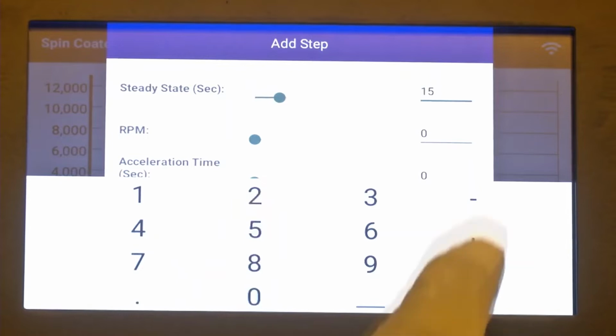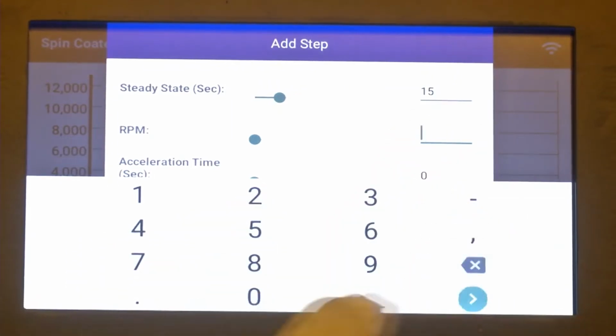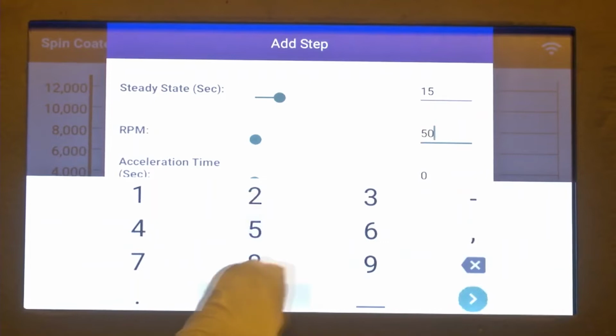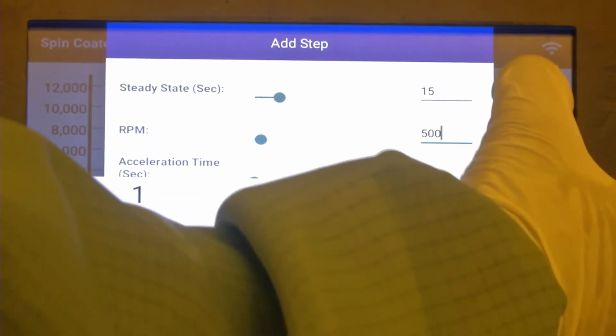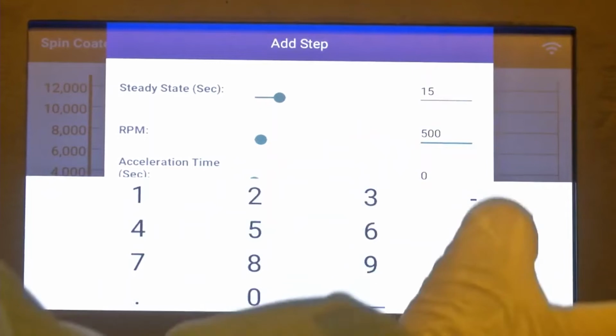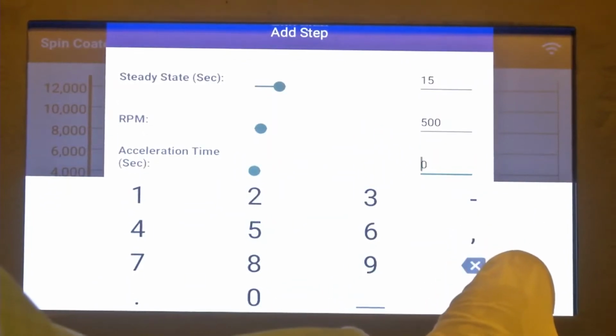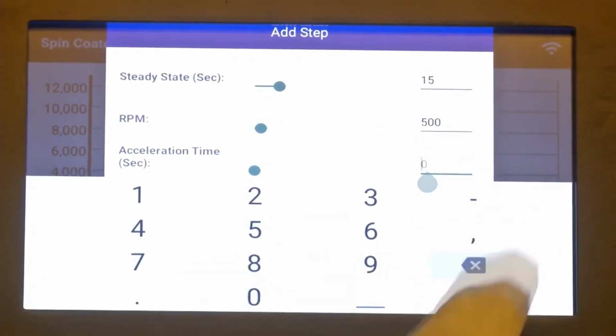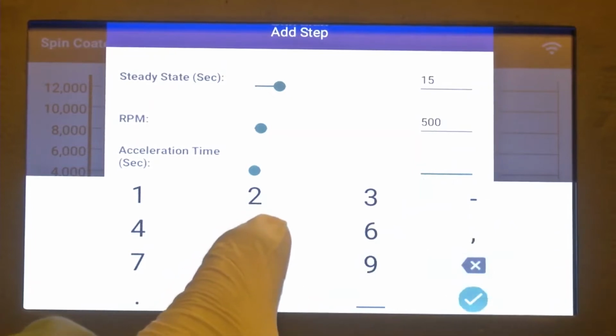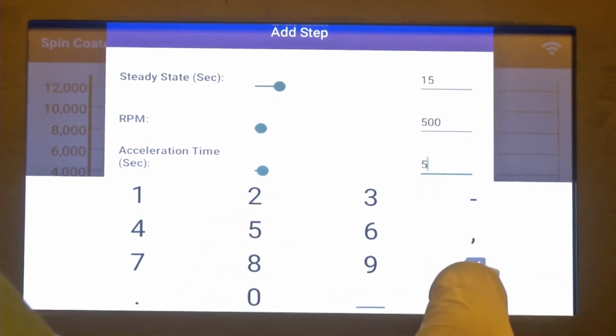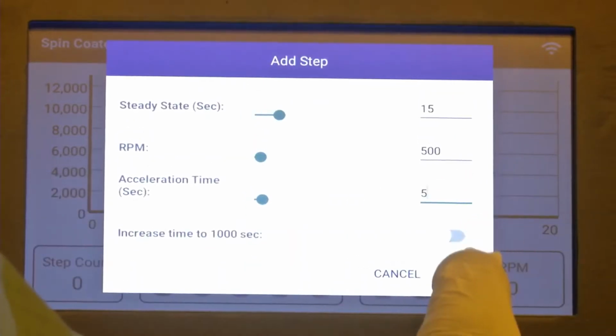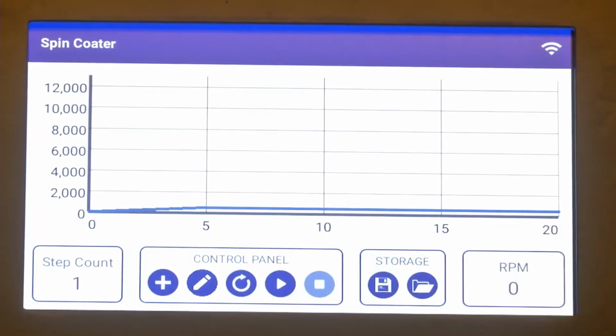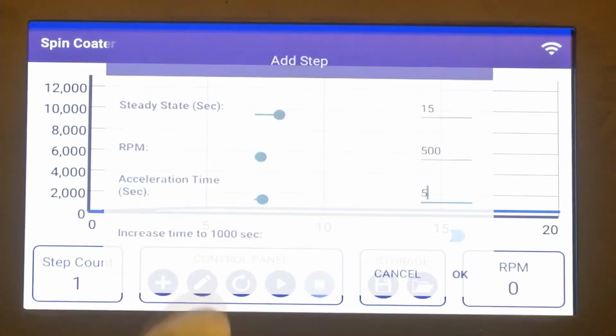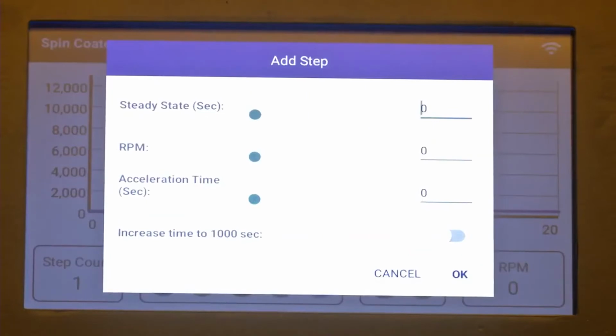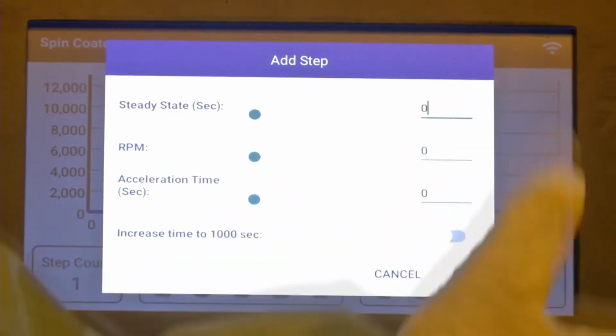So as we can see, as of now we have given 15 seconds of rotation at a particular speed. The speed we have decided in RPM, 500 RPM, is the first. What this particular step will do is spread the precursor uniformly on the surface, and we can give the acceleration as well. Once that is done, the next step is to give the higher speed step to ensure that the solvent which is spread uniformly can now be evaporated and thinned down.